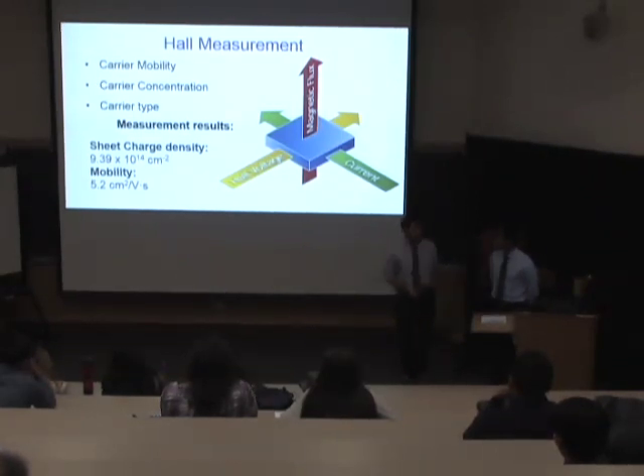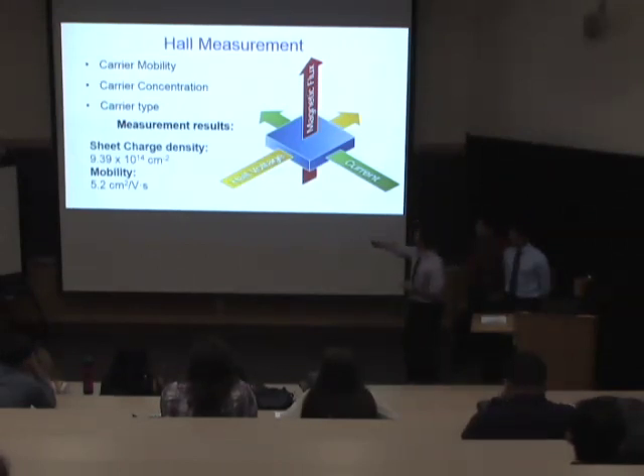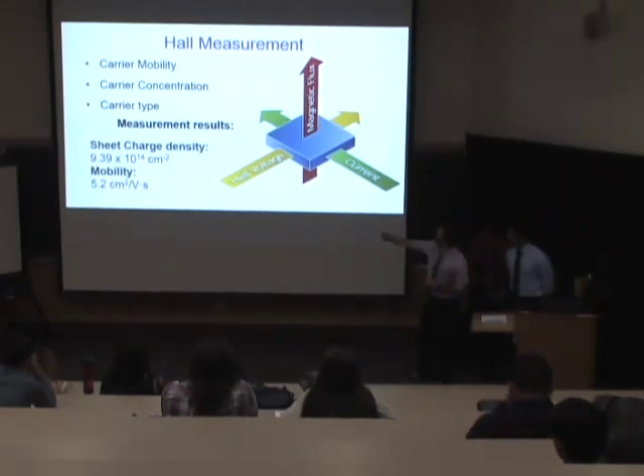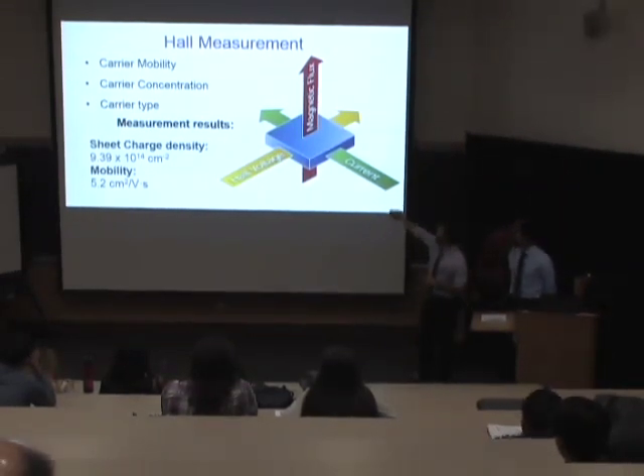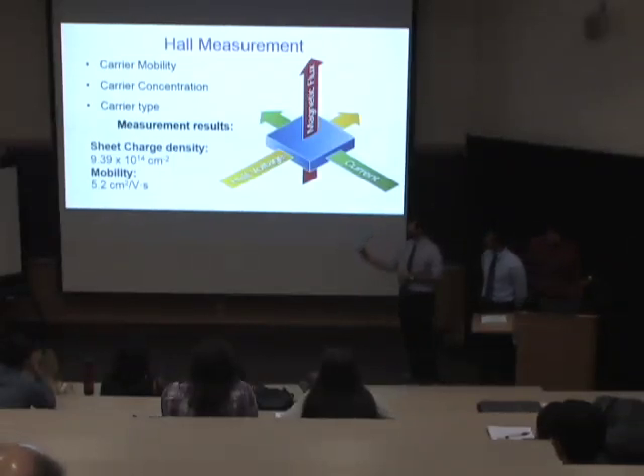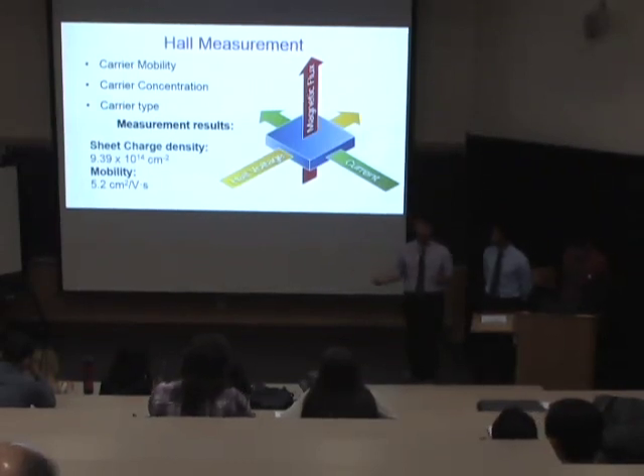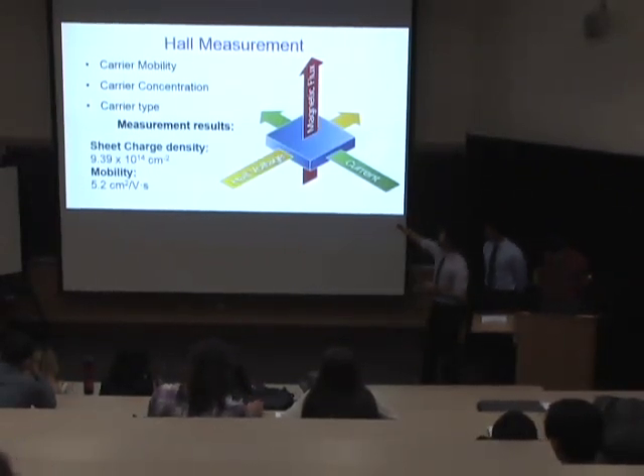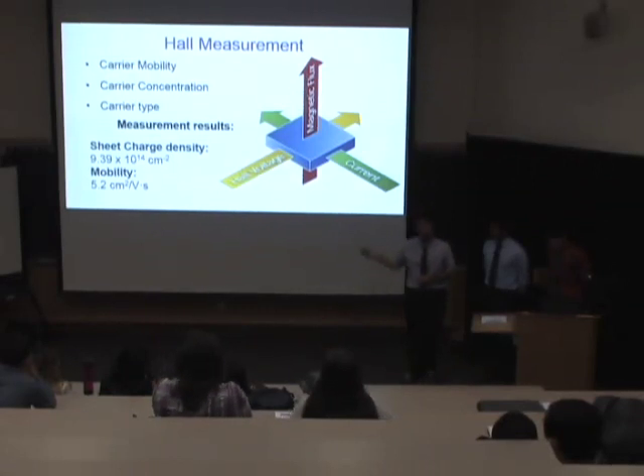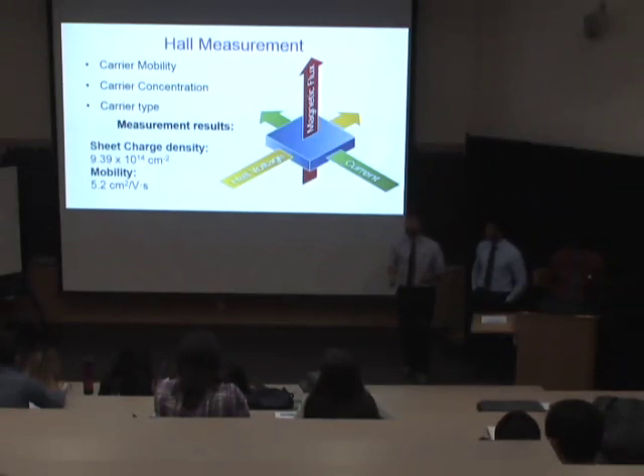Hall measurements are almost a surface voltage that, when you have a magnetic flux applied to our material and a current at the same time, produces a voltage perpendicular to both of these two. If you think of the right-hand rule, it's a vector that's perpendicular to 2 perpendicular vectors. It produces this Hall voltage, which is important for measuring things like carrier mobility, carrier concentration, and carrier type. A carrier is a positive or negative charge that moves through a material.